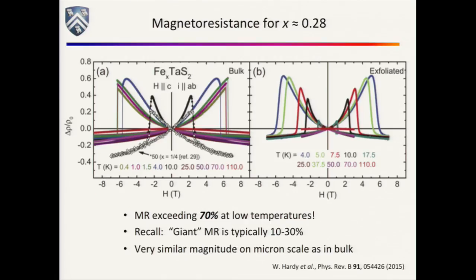What's surprising is here's the magnetoresistance of the bulk and the exfoliated piece. And this time, I'm not multiplying the change in resistance by anything. The magnetoresistance of this stuff is on the order of 80%. Okay? That's really 70 to 80% at low temperatures. That's big, right? If you recall, giant magnetoresistance is typically 10 to 30%. So we've kind of run out of superlatives in the magnetoresistive world.